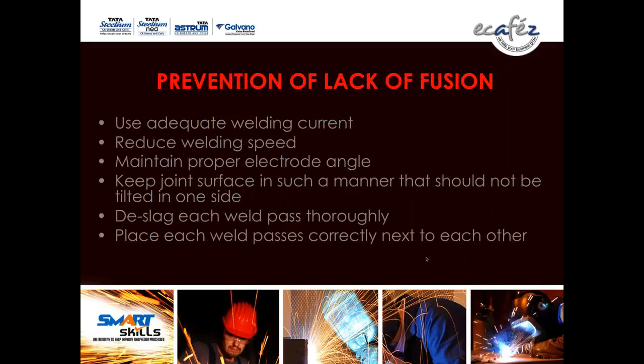Prevention of lack of fusion: use adequate welding current in your joint. Reduce welding speed. Maintain proper electrode angle. Keep the joint surface in such a manner that it is not tilted to one side. Deslag each weld pass thoroughly. This is very important. Place each weld pass correctly next to each other.